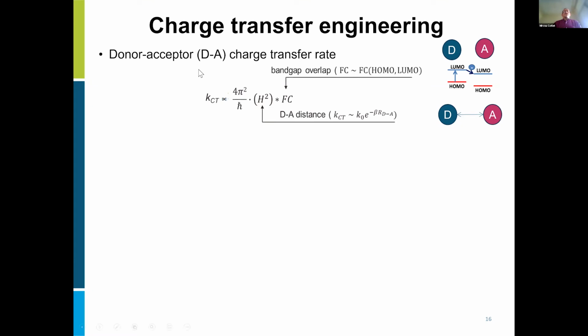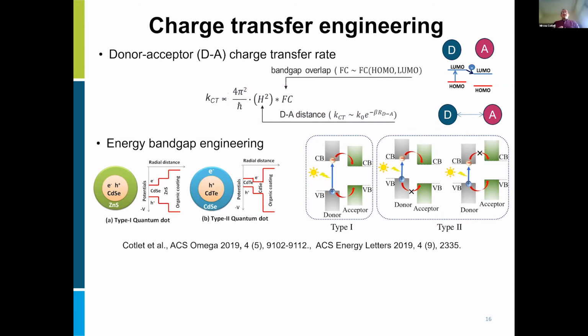And in doing that, we have a kind of simplistic, I would say, design or path that we follow. We look at the charge transfer rate here on the donor acceptor system, and we see that in the most simplistic way, there are two terms here. One relates to the energy band gap overlap between the two constituents, the donor acceptor here. For example, in this particular case, in this image, it is going to be the conduction band between the donor and acceptor. So if we can vary this gap here, we can vary the driving force for the charge that moves from the donor to the acceptor. There's a second term here, actually, that relates to the distance between the donor and acceptor. If we can vary this, we can also control the charge transfer. So we have two ways: energy bandgap engineering and distance engineering.